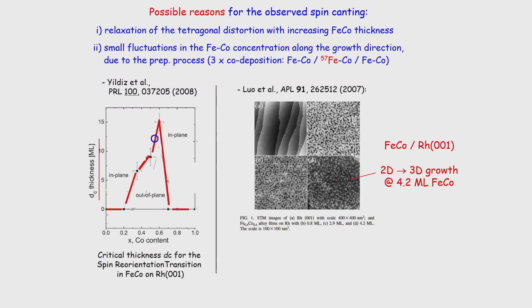But why? How can we explain that? Well, I think the explanation is that this group has shown that for iron, cobalt, and rhodium, starting from 4 monolayers, the growth changes from 2D to 3D. The islands that start to appear can explain this canting, okay? This is what we suppose explains the canting that starts to appear when you look by Mossbauer at monolayers away from the interface.